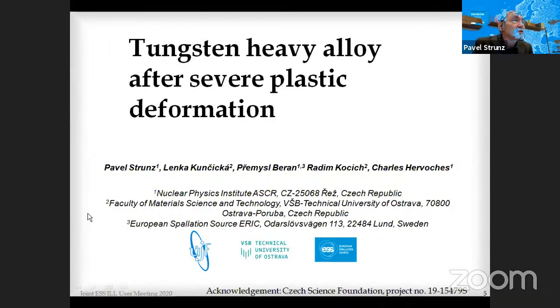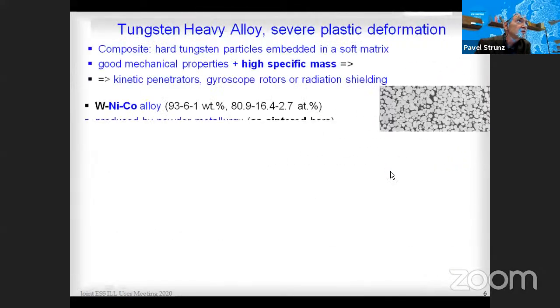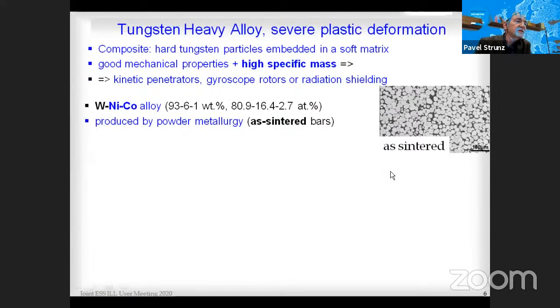It's about tungsten heavy alloys, which is an important material. And I listed here also the people who collaborated on this research and to whom I am thankful. So tungsten heavy alloys are in fact composites where hard tungsten particles are embedded in a soft matrix. They have good mechanical properties, high specific mass, and therefore they are quite suitable for kinetic penetrators, gyroscope rotors, and radiation shielding. We particularly investigated tungsten alloy, which contained nickel and cobalt, and which was produced by powder metallurgy.